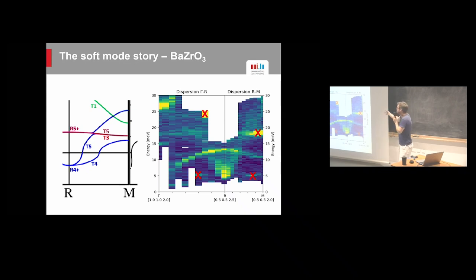So this is what measuring dispersion looks like. What is a bit unusual on this plot is the damping, really. Typically, in a very nice crystal, you would be able to follow the branch in a much easier way. But here we are talking about a crystal that's quite small by neutron standards. So counting time was really an issue, and also the mode is really damped.